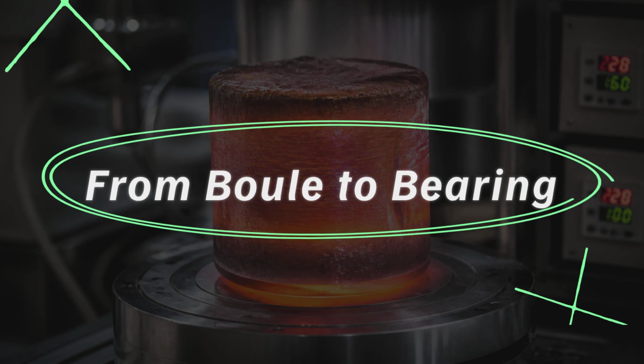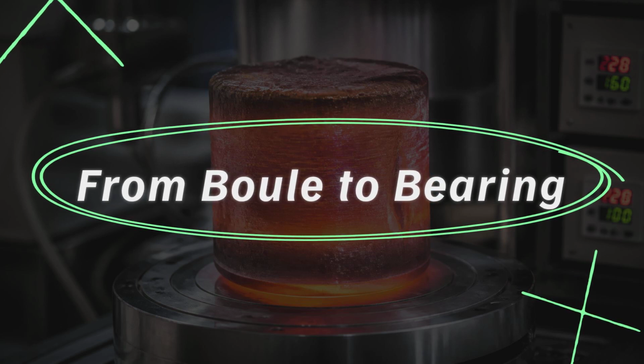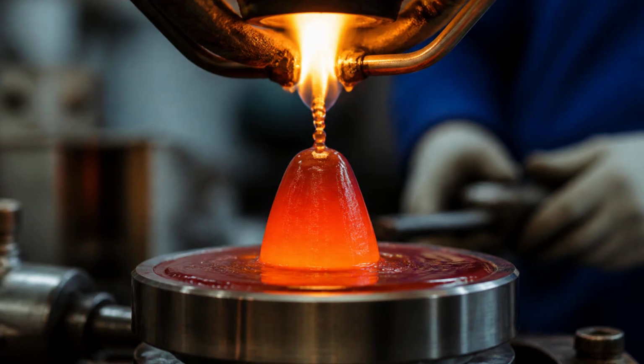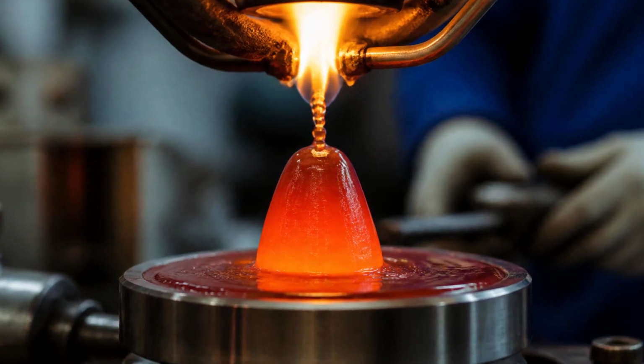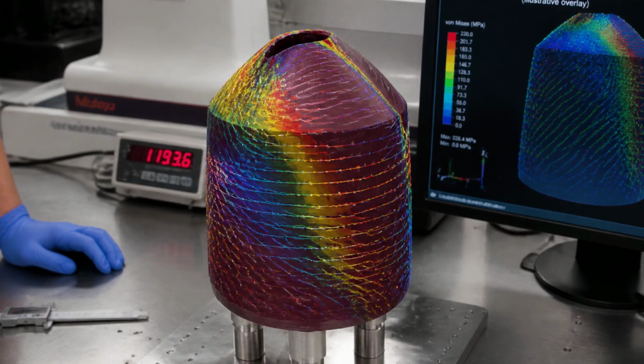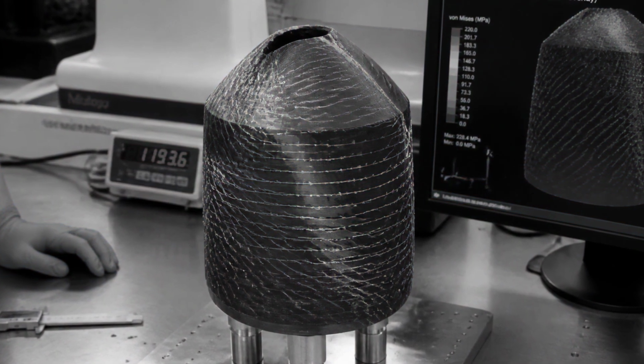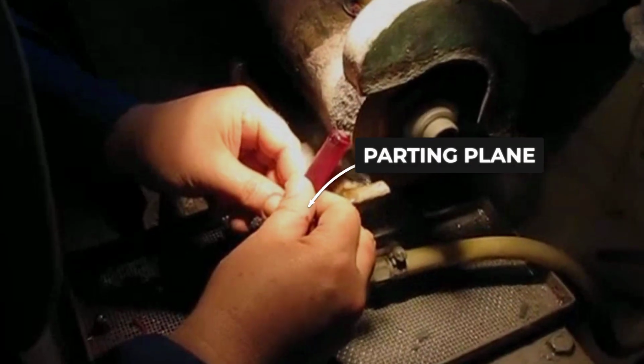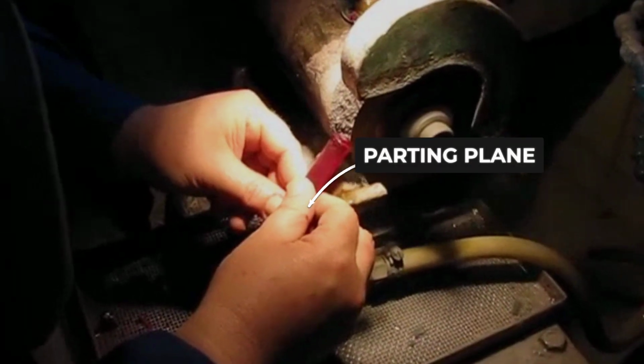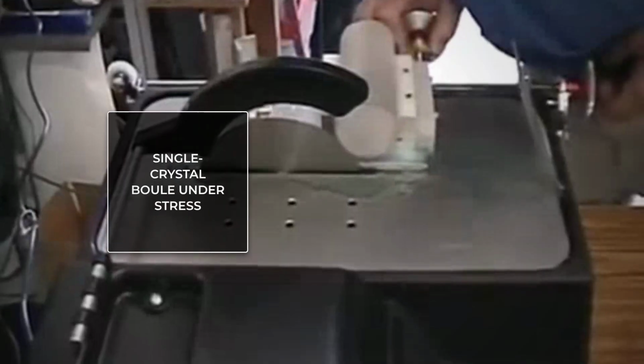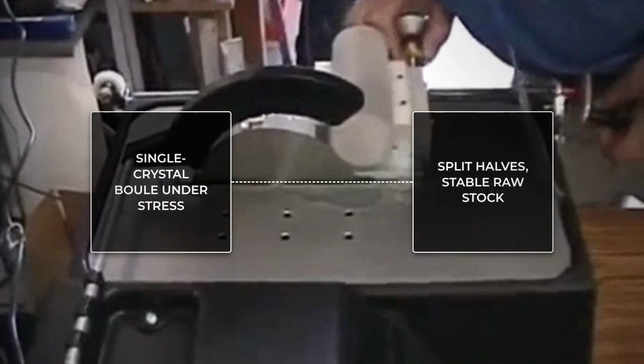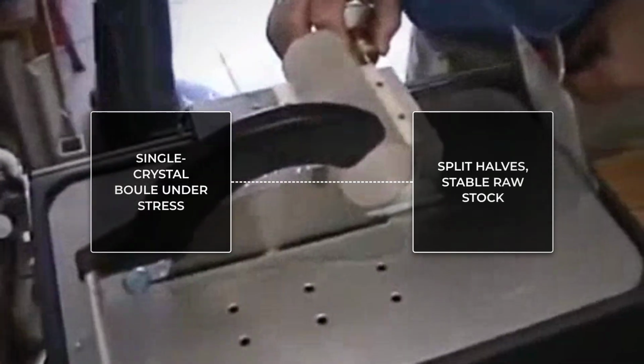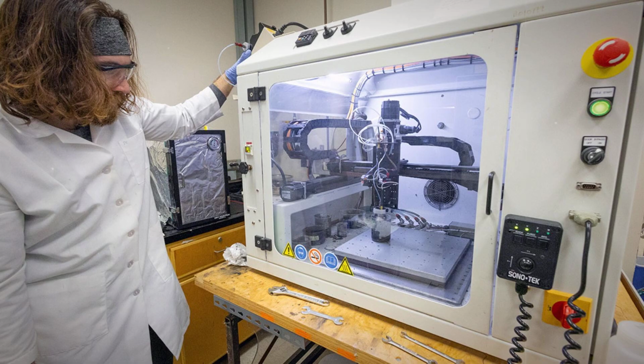Once cooled, the solid corundum boule cannot be immediately sliced. The extreme thermal gradients of the flame fusion process lock massive internal stresses within the crystal lattice. To prevent spontaneous shattering, a technician splits the boule lengthwise along its natural parting plane, releasing this tension. This clean split transforms the single crystal into stable, raw stock, ready for the machining floor.